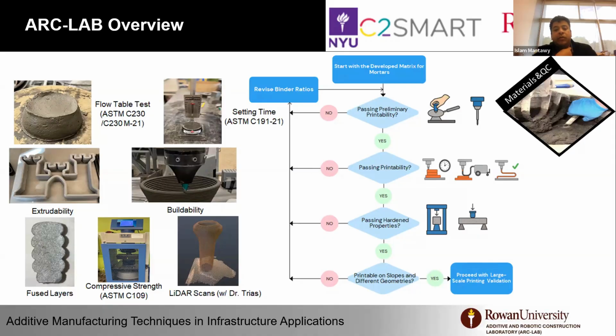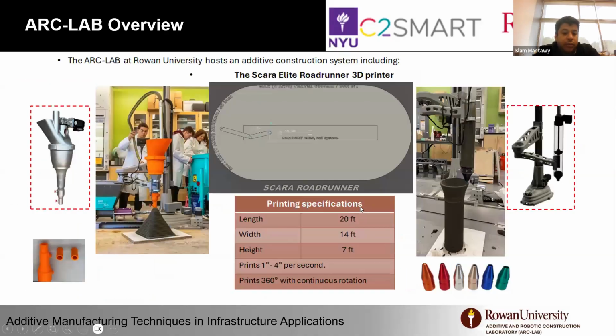So this material was developed about 2 years ago, and we use it on all our material. Our compressive strength in casting is around 9 to 10 ksi. As printed, it will go a little bit less because of the anisotropy introduced, so it goes to 7 to 8. With steel fibers, it can be even much higher. So you can see here a cross section of fused layers on the left side, and it's a totally different way of designing, but you have limitations based on the equipment that you are using, especially particle size. Okay, thank you very much.